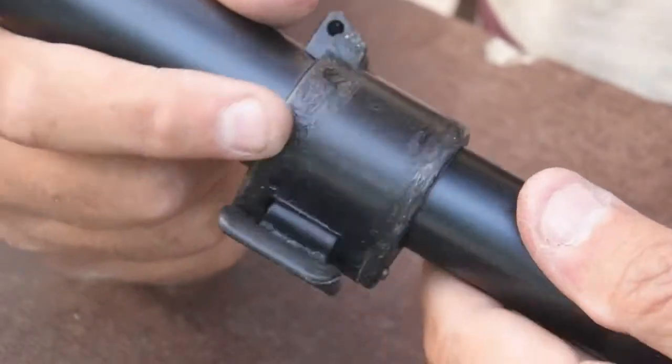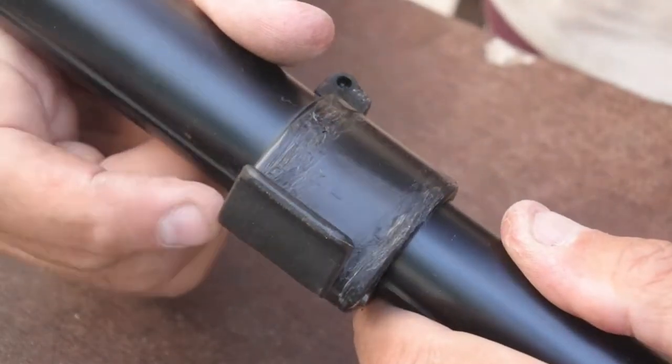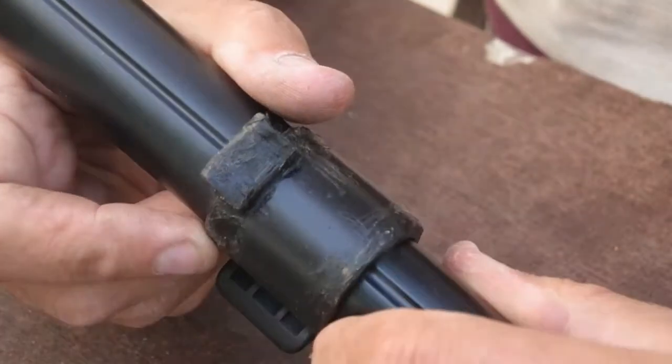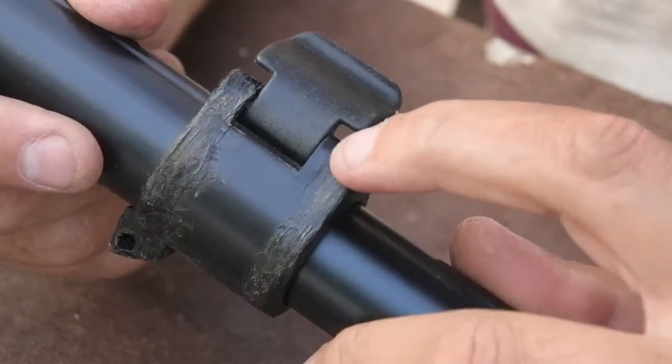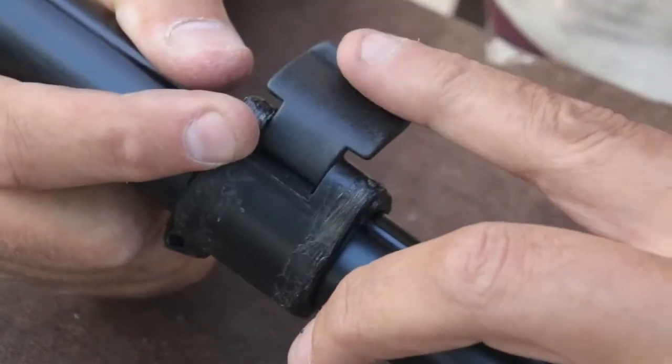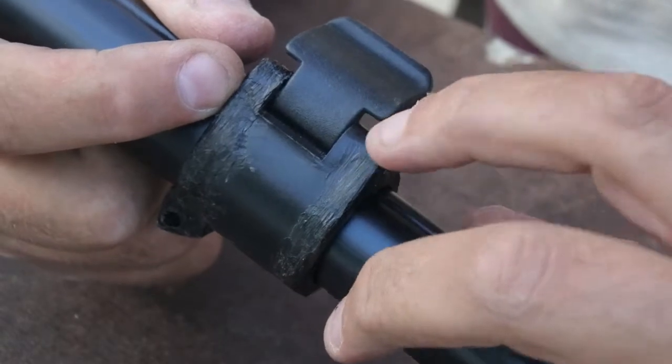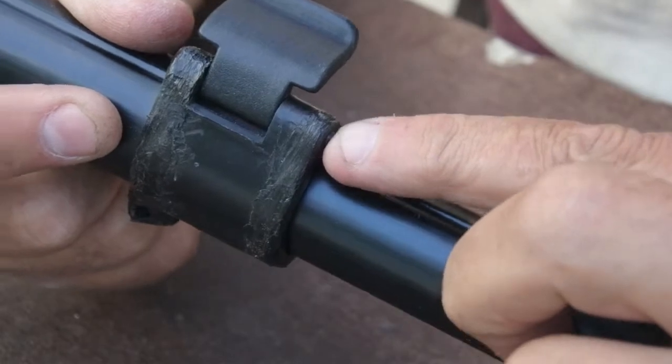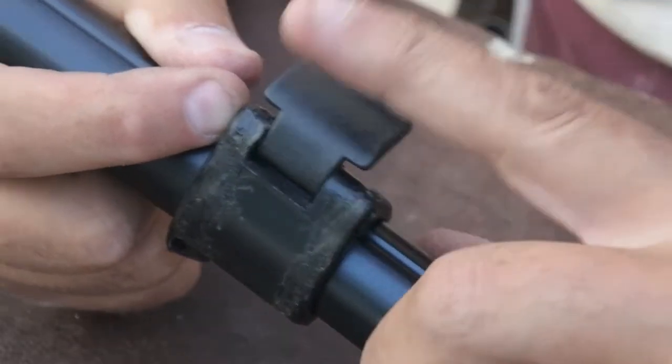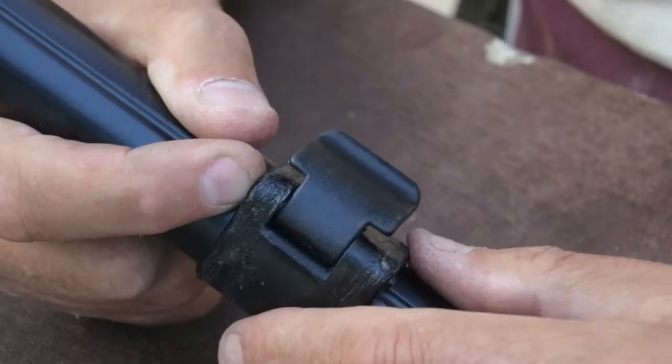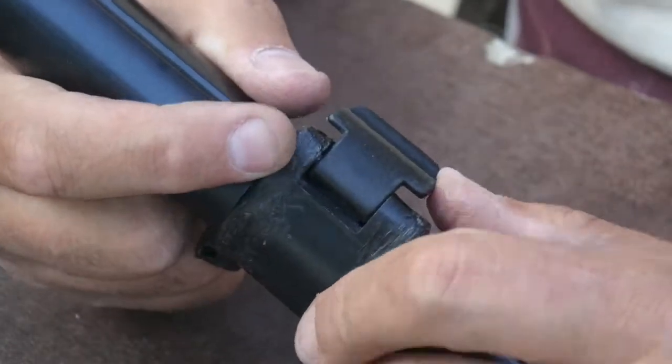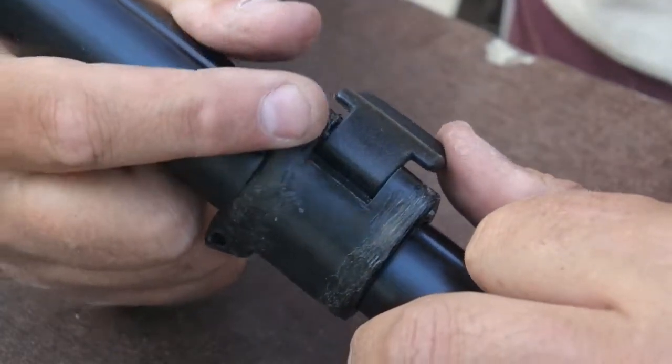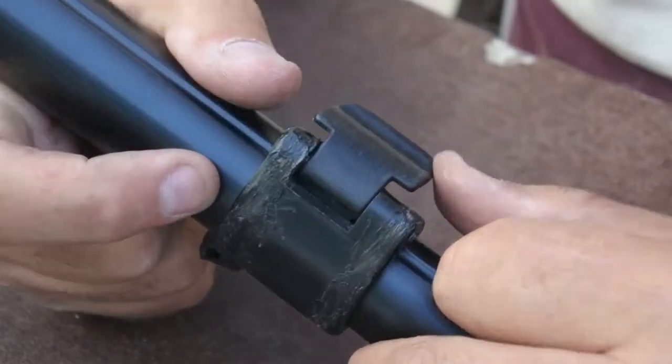I wound and welded the glass fiber all around on both sides of this clamp, especially where the forces will be strongest. There's a bolt or pin going through there, and the leverage from this clamp will drag on this plastic clip. I imagine most of the forces will be around here. That's where the one that broke cracked along this line.